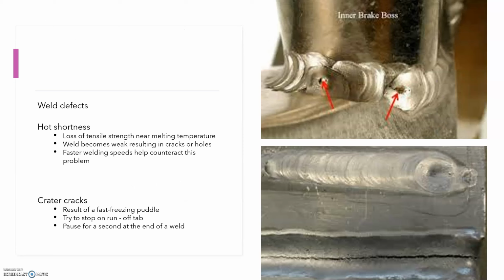On page 9, aluminum has much lower melting temperature than most metals and their alloys. This is why hot shortness is the main problem. Hot shortness is losing tensile strength in the material near the melting temperature, resulting in cracking. Welding faster reduces heat input, which can help reduce hot shortness. And crater cracks are also common.